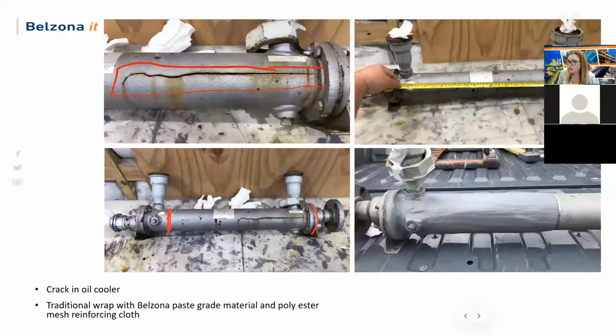Here's an example on an oil cooler. You can see the crack was pretty significant, and the asset owner wasn't able to weld this or do any other application due to the oil being too dangerous to weld with it built up. They needed this back. They weren't able to get another piece of equipment for weeks. We were able to return it with Belzona paste grade composite wrap around it in 24 hours.